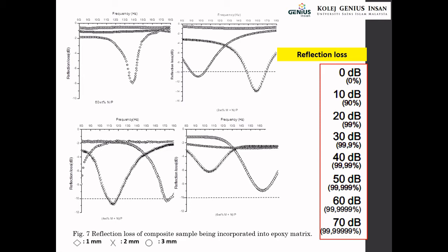the reflection loss shifts towards a much lower frequency range. For example, this is 2 mm and 3 mm. So as we increase the thickness, the reflection loss moves towards a lower frequency range. For 1 mm, it is at a much higher frequency range and it cannot be seen in the figure.